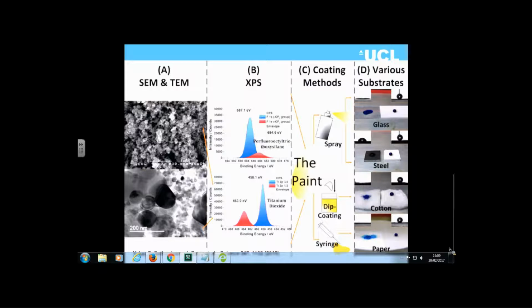In fact, this is something we published in Science in 2015. It's a very simple idea, but just by spray dip coating or syringe extrusion of our dual-scaled nanoparticles onto a surface with an adhesive layer, we create a very stable superhydrophobic surface - one that you can even rub with sandpaper 40 or 50 times and it will still function.